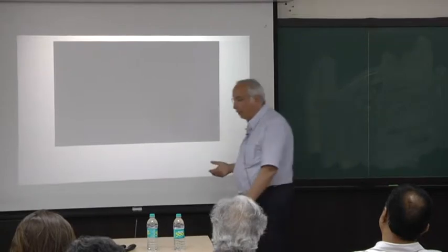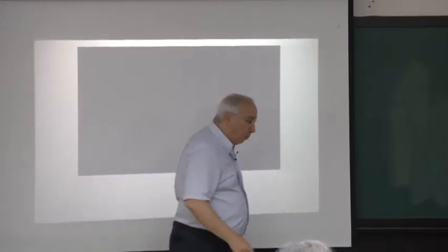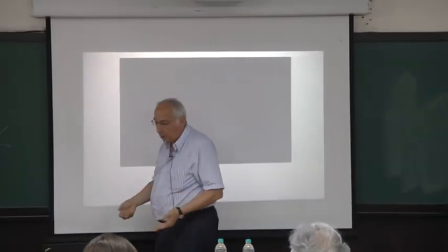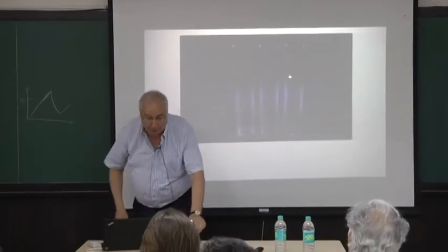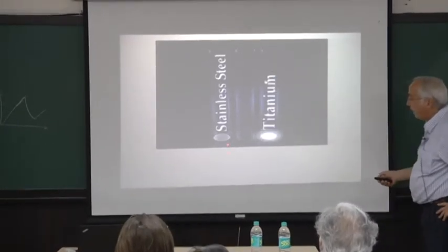What Bill Johnson has done at Caltech, which is a simple but ingenious idea, is to take more than two, like four, five, even six different metals, mix them together, and then you could get a glassy state by cooling even at 10 to the 2 Kelvin per second. And okay, so now I'm going to show you an experiment in which we're going to throw a metal ball into three tubes where the bottom is either titanium or steel or metallic glass, and see what is going to happen here. So these are the three tubes. This has the stainless steel at the bottom, this is titanium, this is metallic glass, what Bill Johnson called liquid metal, because that's the name of his company that makes a lot of money, by the way.